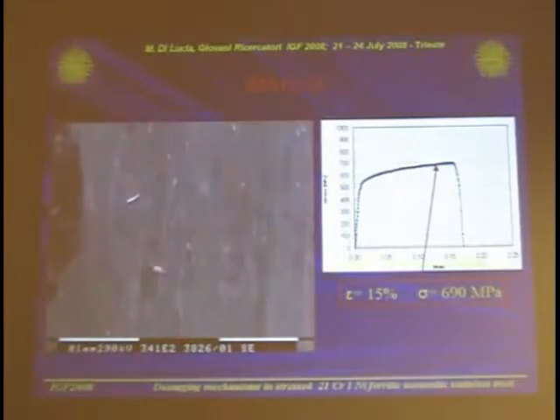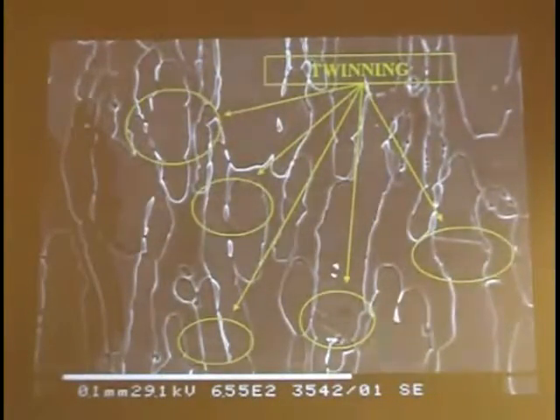The following figure shows the 21 chromium 1 nickel duplex stainless steel microstructure, which is constituted of austenitic islands, light gray, in a ferritic matrix, dark gray. Then some images obtained during microtensile tests are reported. It is possible to observe the deformation of the austenitic grains and the presence of slip bands, both in ferritic and austenitic grains, which start from low deformation conditions, and their density increases more and more as deformation increases. Then it is possible to observe twinning in the austenitic phase.